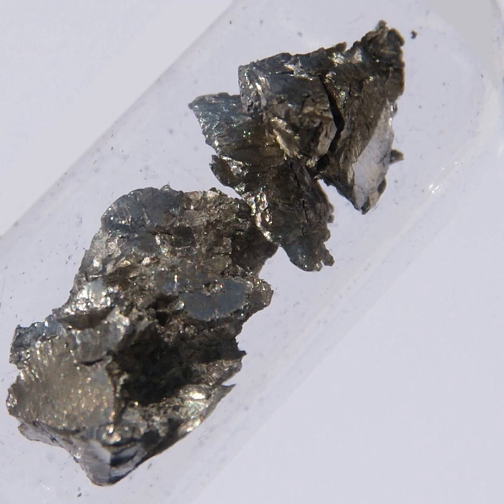fluoride with fluorine gas, producing Na2PrF6, following which sodium fluoride is removed from the reaction mixture with liquid hydrogen fluoride. Additionally, praseodymium forms a bronze diiodide, like the diiodides of lanthanum, cerium, and gadolinium. It is a praseodymium(III) electride compound. Praseodymium dissolves readily in dilute sulfuric acid to form solutions containing the chartreuse Pr3+ ions, which exist as [Pr(H2O)9]3+ complexes.